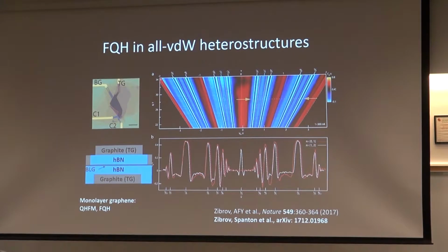I'll digress for just a second and answer your question of why that's an interesting question. This is a monolayer graphene device. It has a large energy gap, about 30 millivolts that we measure at zero magnetic field. Very well developed fractional quantum Hall starting from about a Tesla. And due to this energy gap in part, there's also even denominator fractional quantum Hall physics that appears in monolayer graphene. Do we think it's due to some phase transition that's ultimately related to the size of this energy gap? Lots of knobs to turn. Some of them we understand, some of them we don't. From a material science point of view, we don't really understand. You have some of the advantage of gallium arsenide with the gap in graphene. A lot, yes. You can certainly realize that limit.